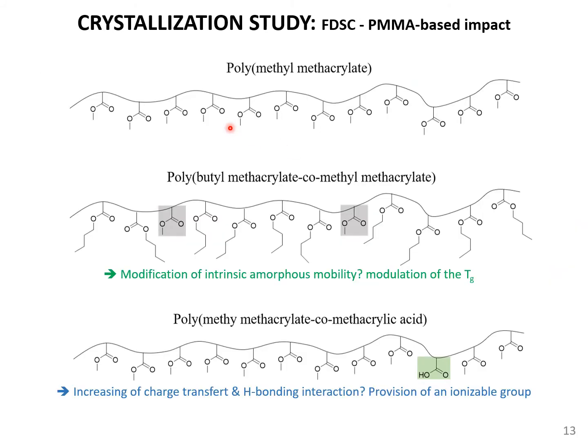So this is a comparison that we wanted to make between a copolymer containing butyl methacrylate, in order to modulate the TG of the PMMA, at a very low content around 10%, and another copolymer based on methacrylic acid, in order to introduce some ionizable groups at a very low content around 5%.